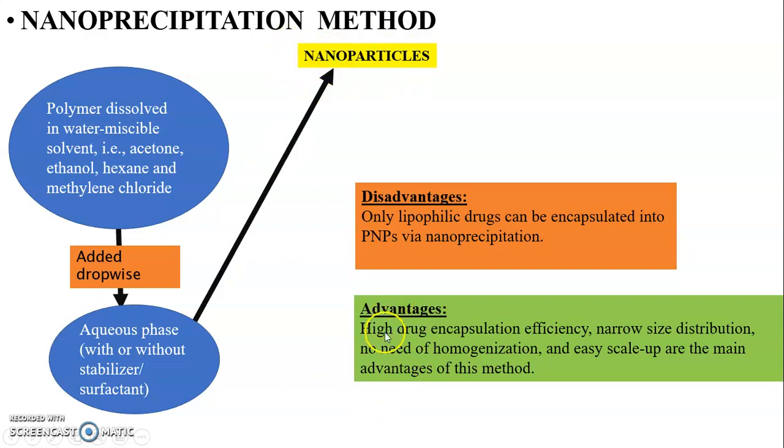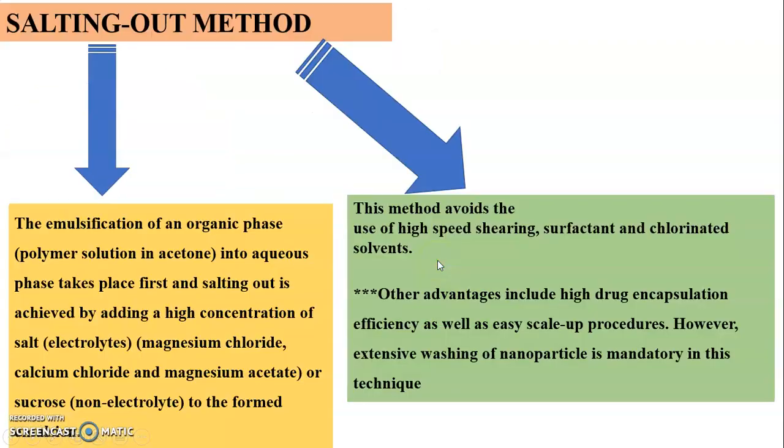The advantage of this method is high drug encapsulation efficiency and narrow size distribution. There is no need of high homogenization, and easy scale up is the main advantage of this method. The disadvantage is that only lipophilic drugs can be encapsulated into these PNPs by nanoprecipitation.